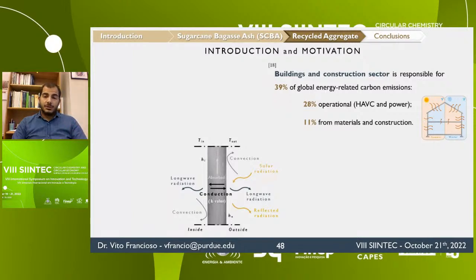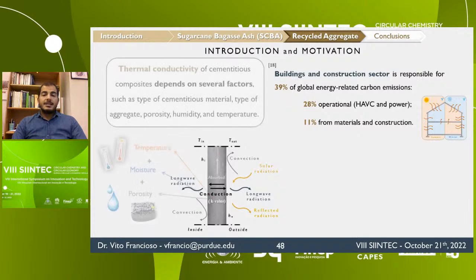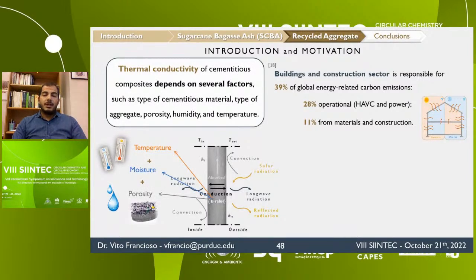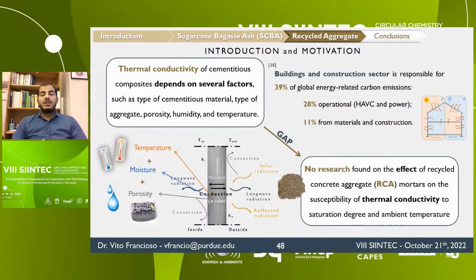Therefore, enhancing the thermal insulation capacity of cementitious composites used in building construction might reduce the energy consumption of buildings during their service life. It is known that the thermal conductivity can be reduced by replacing natural aggregate with recycled concrete aggregate, which has a lower thermal conductivity. However, no research was found on the effect of the recycled concrete aggregate on the susceptibility of the thermal conductivity to saturation degree and ambient temperature. Why is it important? It is important because understanding these effects is crucial to assess the actual environmental impact during the service life as a part of the building component.